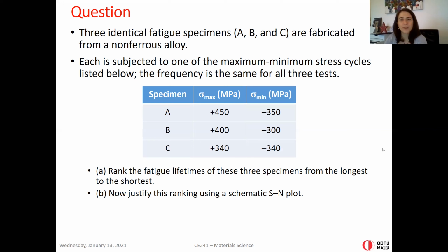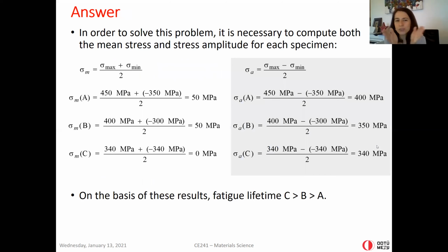Please pause the video before going on. Okay, in order to solve this problem, first of all, we need to compute mean stress and stress amplitude for each specimen. Mean stress is basically the average. So for A, B, and C, it is calculated as 50, 50, and 0, respectively. And we also need to calculate the stress amplitude. It is max minus min divided by 2. So for A, it is 400 megapascal. For sample B, it is 350 megapascal. For sample C, it is 340 megapascal.